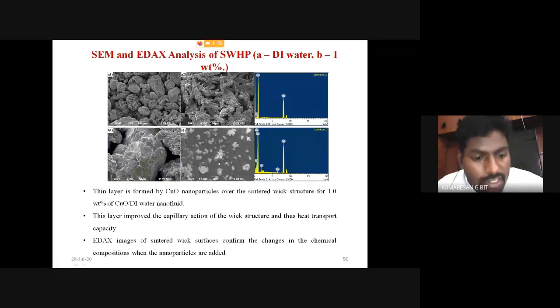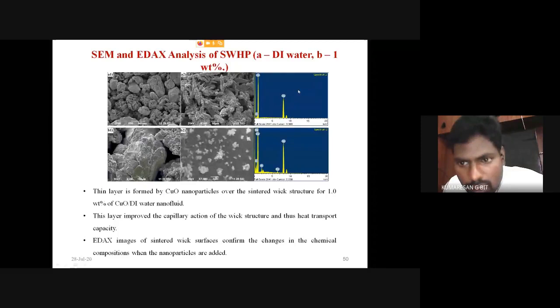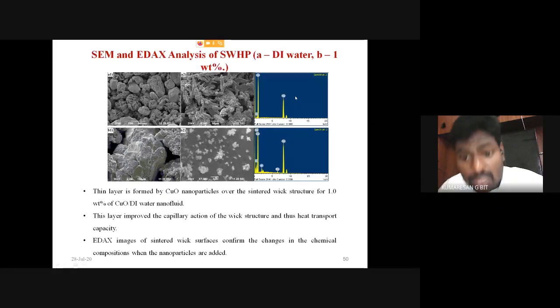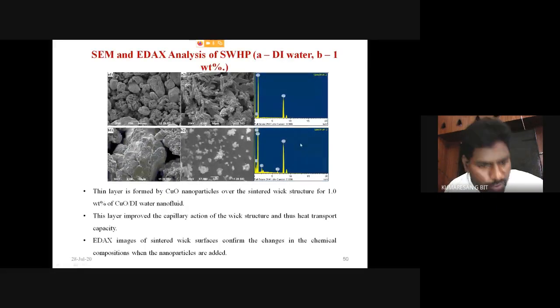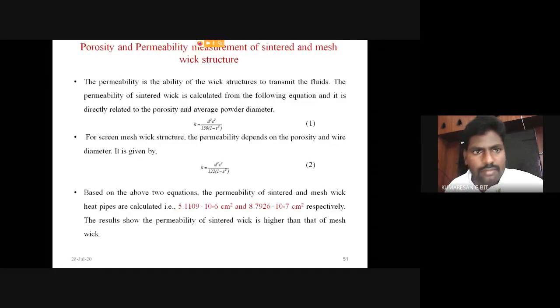The EDAX composition images of the sintered wick surface confirm the changes in the chemical composition when the nanoparticles are added in the heat pipe. You see in the EDX analysis, between the wick structure used in a normal heat pipe and in the nanofluid heat pipe, the chemical composition of the wick structure is varying. This shows that nanoparticles are additionally added for the experimentation.